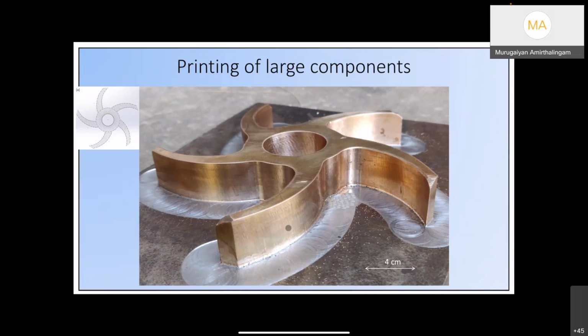and these components, if we don't control the microstructure evolution, would invariably possess differences in mechanical properties as a function of direction. So if you just start depositing simple weld beads, you may get the final shape of the component after post-processing machining. But when we actually use this component in service, the properties are not as good as the conventionally made component, isn't it? So the moment you use this impeller in service, it will just crack, and the service time will be much lower than the conventionally made component.